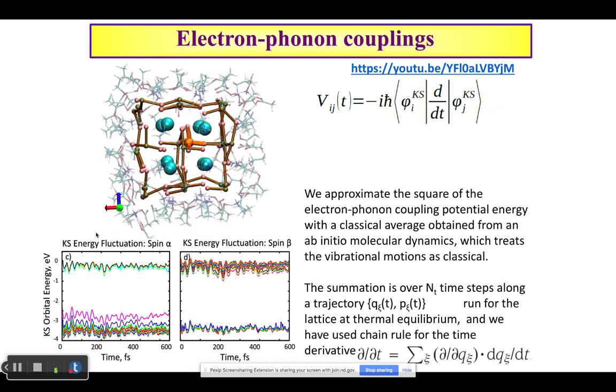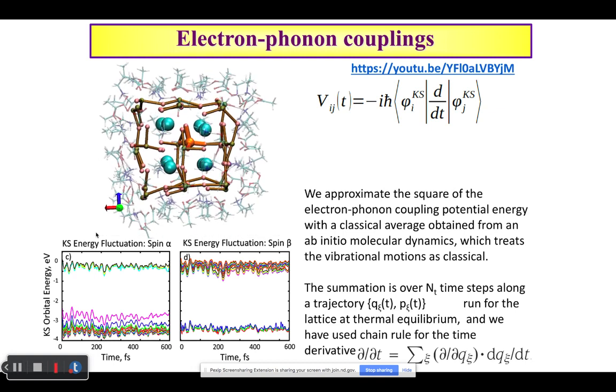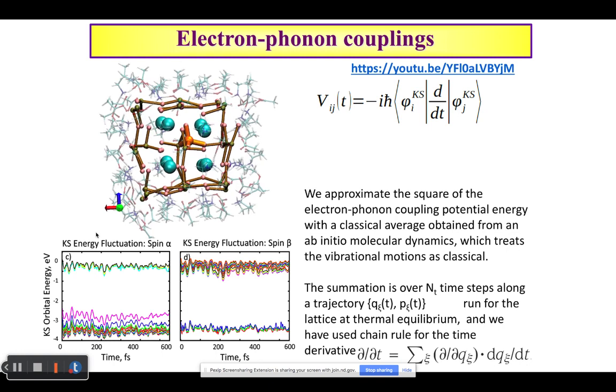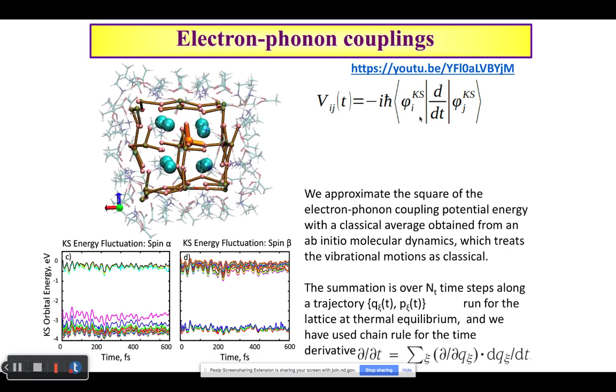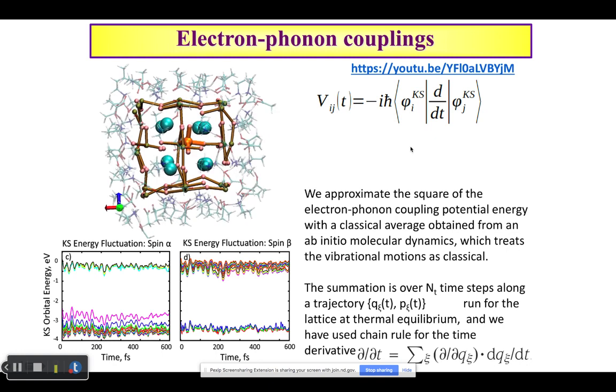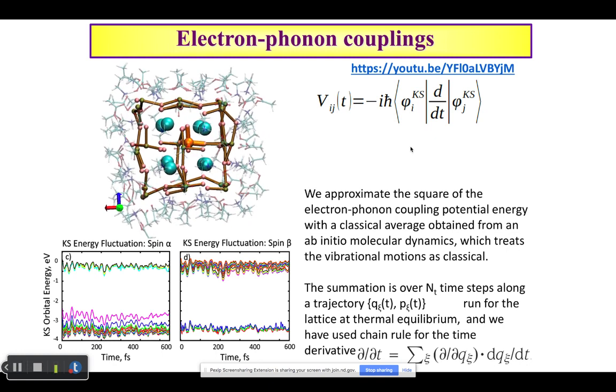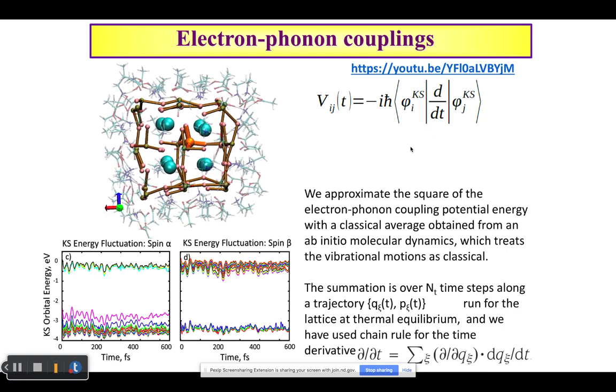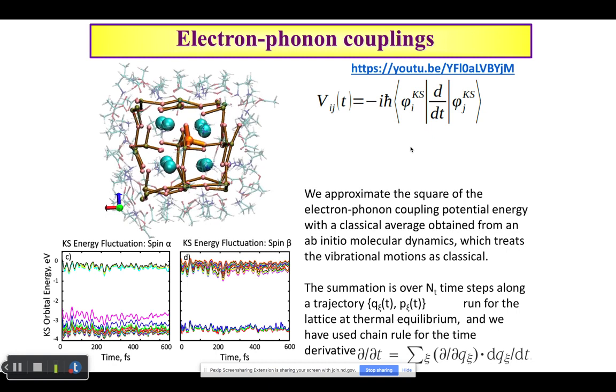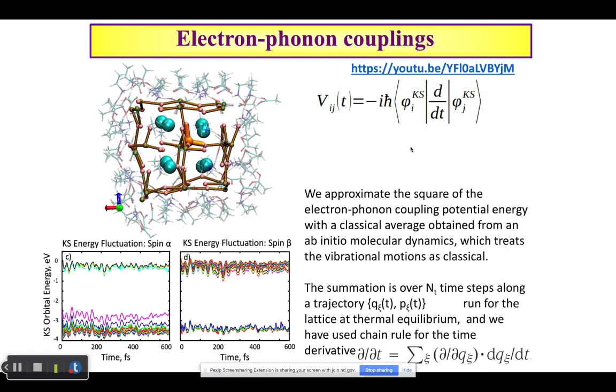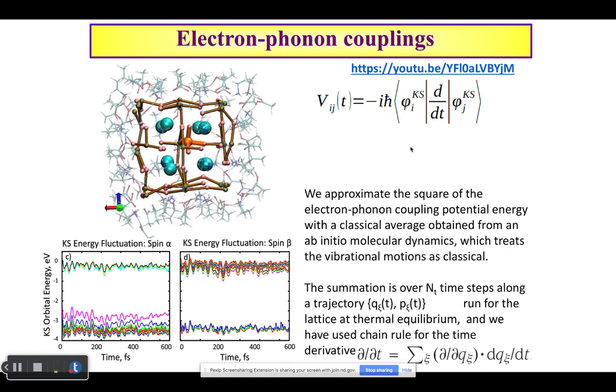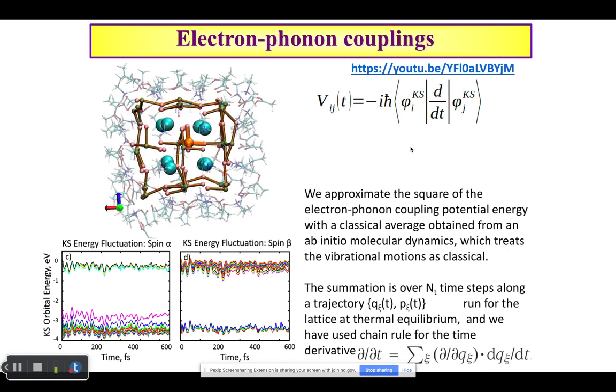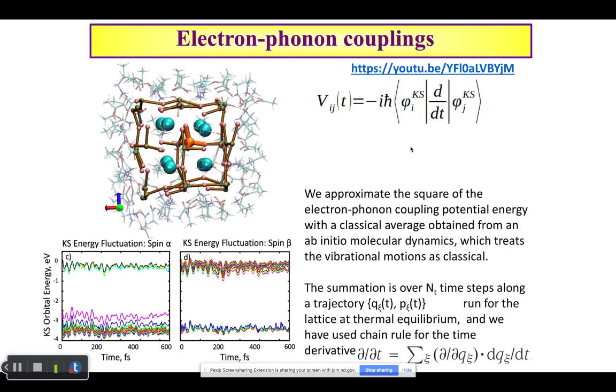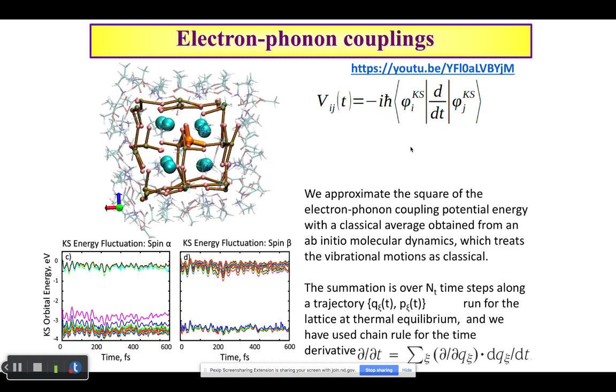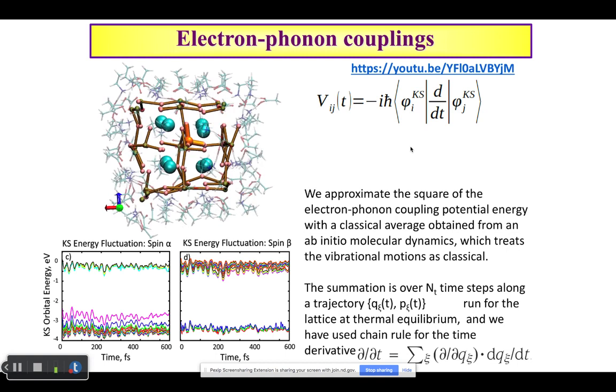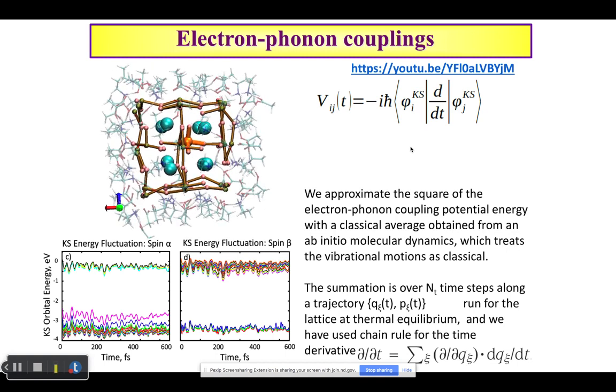So thermal motion is a reason for violation of orthogonality between orbitals. Orbitals before and after some delta t time are not orthogonal, and it gives rise to probability of transition between these orbitals. And we can plug in these so-called non-adiabatic couplings and run electron dissipative dynamics, where these rates allow electronic energy to be dissipated to the lattice and slowly jump from more excited to less excited states.